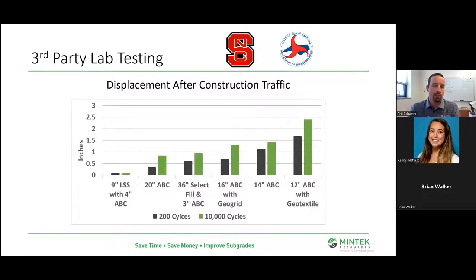And you can see on the far left, the 9 inches of lime treated soil with 4 inches of aggregate base course on top, really hardly saw any displacement after the construction traffic. I believe that bar is about 1/16 of an inch, maybe an eighth. I have to get my numbers mixed up.